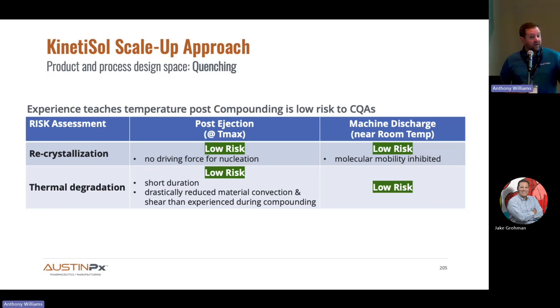But what it means is everything that's made it to the point where I need to scale it up is proven to have survived the quenching process, which involves, at the small scale, an operator manually taking the material, putting it in between some plates, and then taking the heat out of it. So if that happens routinely and effectively at the formulation scale, the machine can do it. And so you can look at these, this is important from the regulatory standpoint, because it's not just about what that SUPAC guidance says, it's about the conversations with the regulatory authorities. What's the risk? That's what everybody cares about.